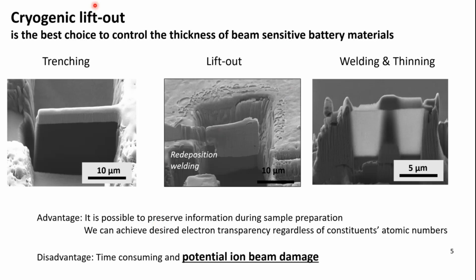Because of the limitations that I mentioned in the previous slide, I believe we need to use the cryogenic lift-out process. Cryogenic lift-out is one way to make a cryo-TEM sample at cryogenic temperatures. In the focused ion beam microscope, we can trench battery materials and perform lift-out. And finally, we can thin down until we have electron transmission.